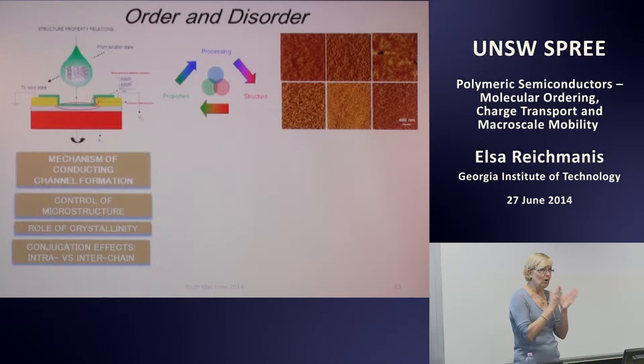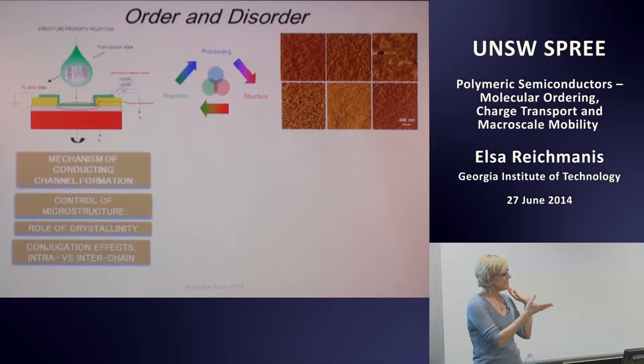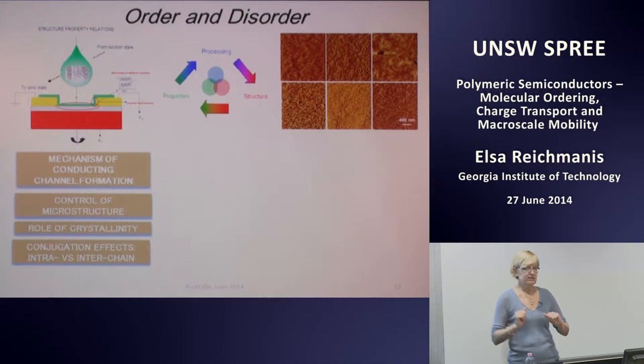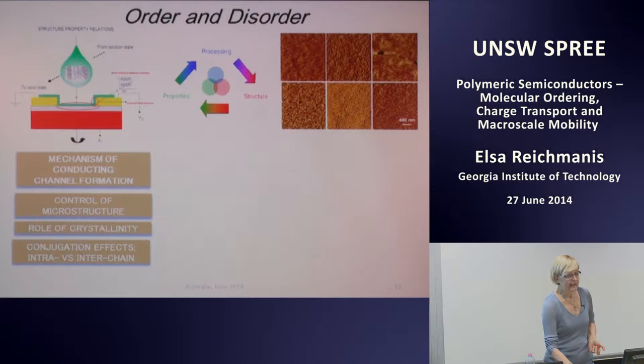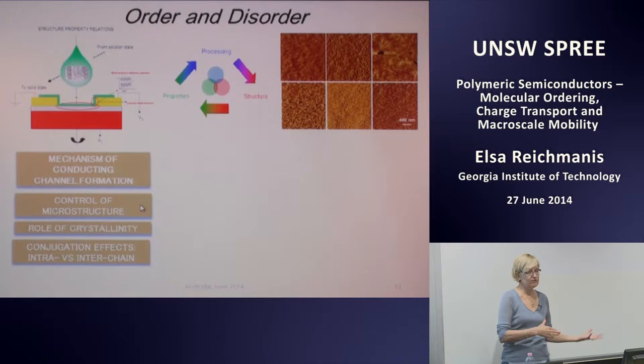The polymer's been put in solution. Different solutions, the solvent may vary. The way that solution has been treated may vary. Once it's deposited on the silicon substrate, the morphology is different in the solid form. All right, so there is some mechanism associated with the formation of the conducting channel. We need to be able to have some control of the microstructure and the nanostructure that's formed.